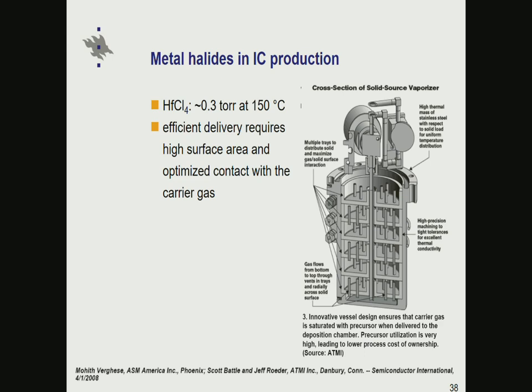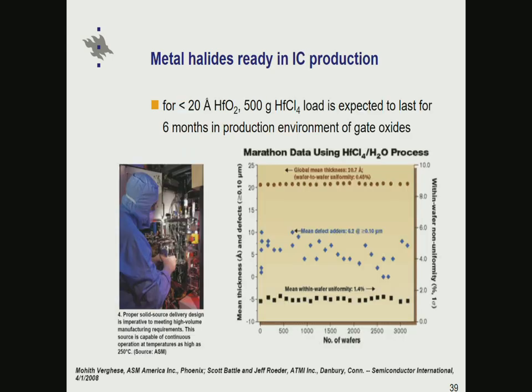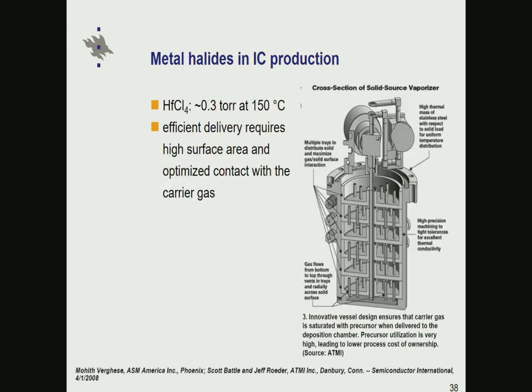To get that operating, ASM was working together with ATMI, as the company was called then. They made a special cylinder with multiple trays on which the solid hafnium chloride was loaded, and the gas percolated from bottom to top to pick up enough vapor for the film deposition to take place. They made marathon tests, and numbers of wafers were given out. Because the hafnium oxide films were something like 20 angstrom in thickness, by loading 500 grams of hafnium chloride into this cylinder, one could keep on running with that load for 6 months in a production environment of these gate oxides. And of course a very important thing here is that hafnium chloride is such a stable molecule that you can keep it half a year at this temperature, no problem at all about decomposition, so it could tolerate much more if needed.